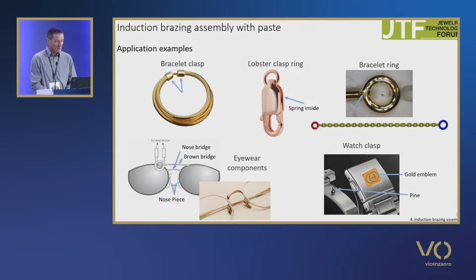Some examples of high-end luxury. Many bracelet clasps are brazed using induction heating to have only local heating. The well-known lobster clasps sometimes have a spring inside. The spring is very sensitive to temperature, so to avoid softening, induction heating is very interesting. The bracelet ring is a good candidate for induction heating because it avoids heating the bracelet a second time, with the risk of the appearance of orange peel or something like that.